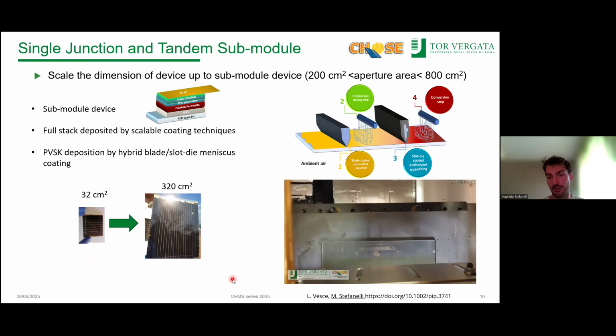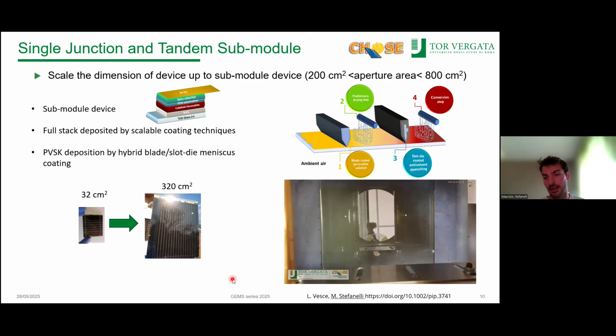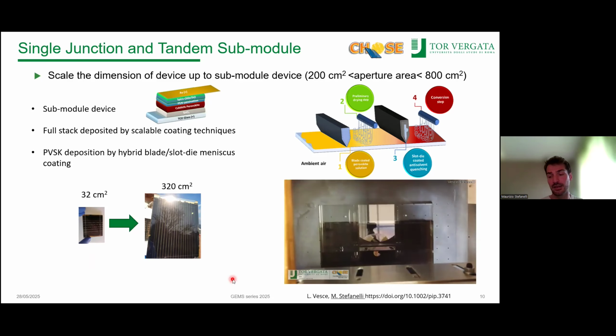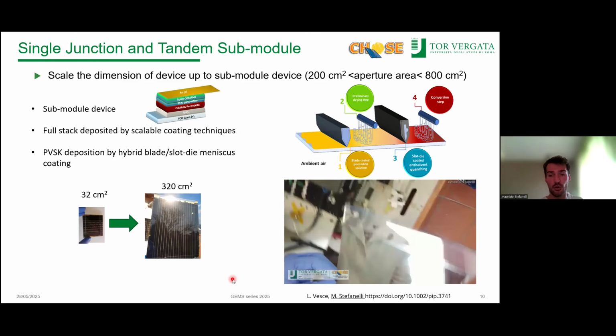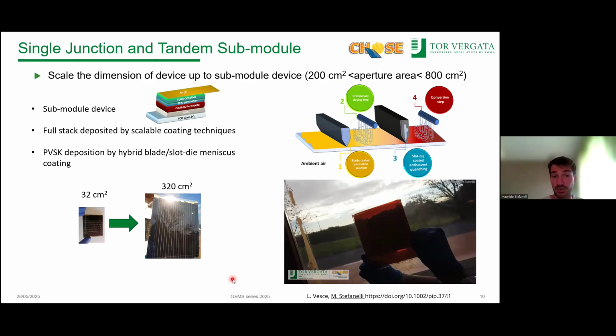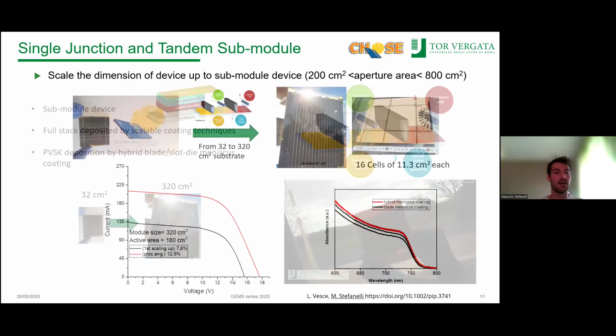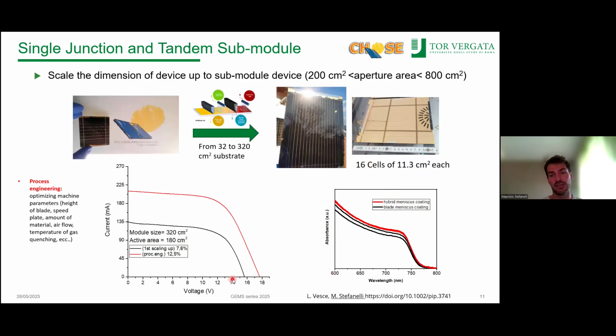So as usual, we have the deposition of the perovskite solution coupled with the air knife to pre-dry the film, and then we did the annealing with the anti-solvent process to get this mirror-like, uniform and shiny perovskite layer. Of course, the optimization from small to large area is not so easy, even if we don't change the environment and the technique. I will just report the main steps that we got in this scaling up.